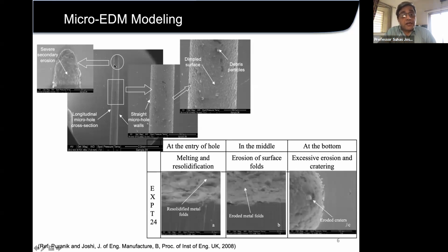So you can see that here the electrode shape has become kind of tapered, and that tapered shape is an indication that the electrode itself is eaten by the process. Instead of the electrode wearing the surface, it is the surface which is eating the electrode. But otherwise, up to two-thirds of the hole is very nicely machined, with very nice dimpled surfaces, and L/D ratios of the order of 10 can be very easily achieved in the EDM process without providing any kind of extra force or mechanism for removal of the debris.